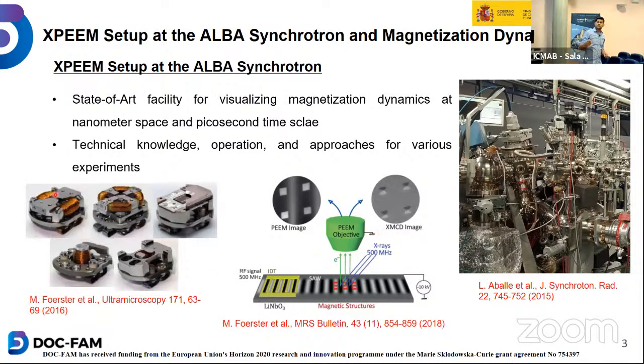You can see here this is in-plane, in which we can apply magnetic fields in the plane of the sample. Here, this is the quadrupole, from which we can apply the magnetic field in any direction. This is the out-of-plane sample holder, in which we apply the magnetic field out of plane, and this one as well. About this one, this is the special sample holder in which we use a PCB. PCB is a printed circuit board, to which we connect the sample to apply electrical signals. So we use this kind of sample holder, and we use the PCB on which we mount the sample and connect it.